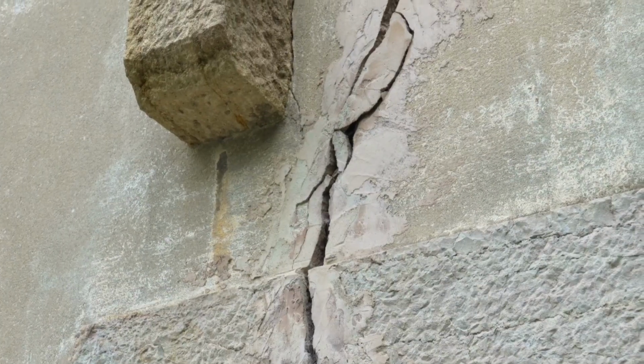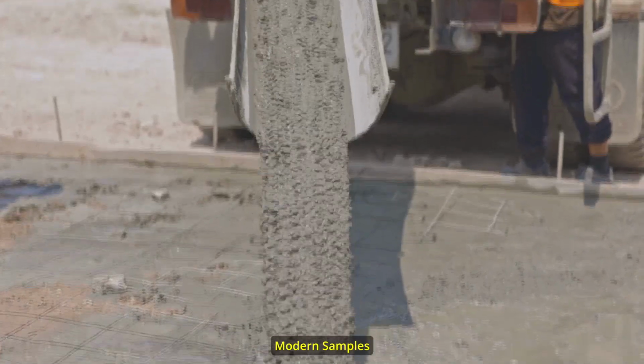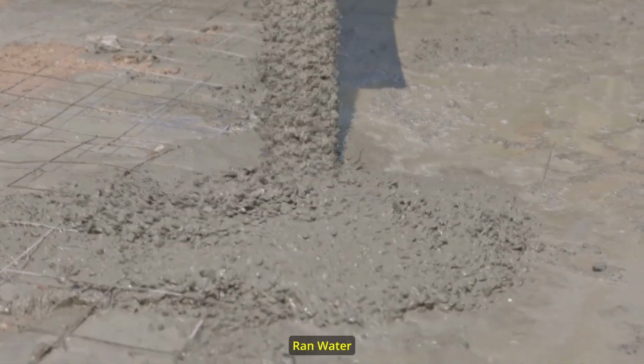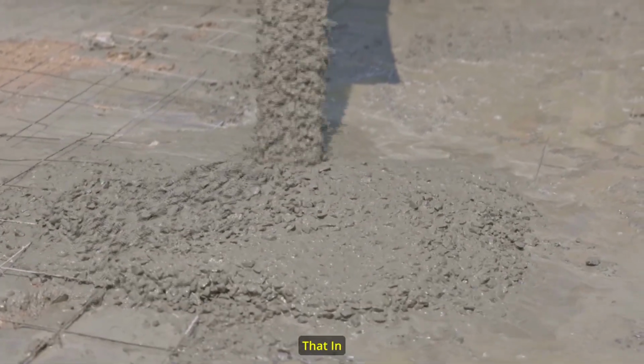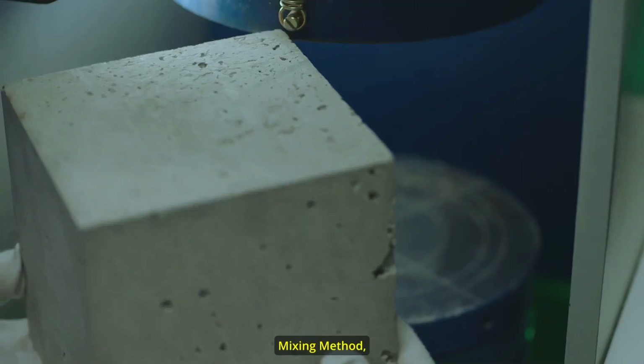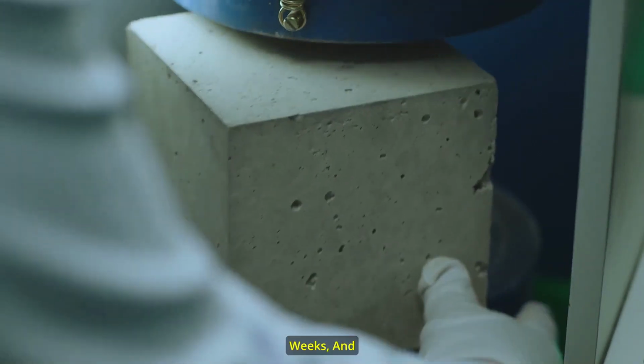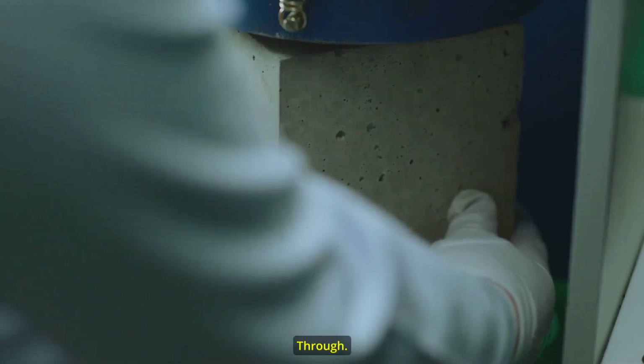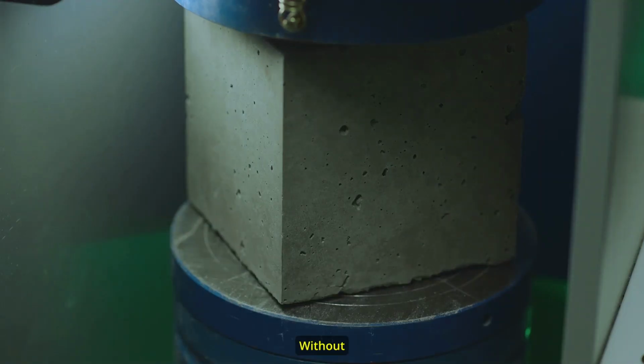In the lab, the MIT-led team made modern samples inspired by ancient recipes, cracked them on purpose, and ran water through the cracks. They reported that in samples made with the hot mixing method, the cracks sealed within about 2 weeks and water could no longer flow through. A control sample made without quicklime did not heal the same way.